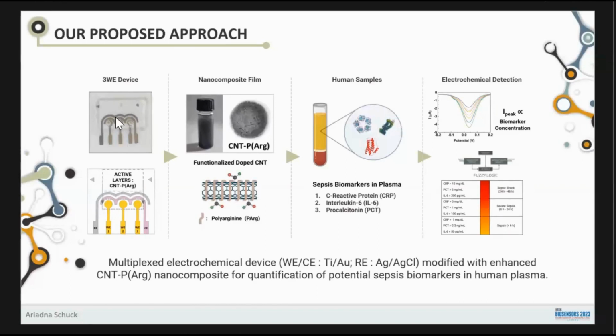But when I put the plasma sample, around 20 microliters, the sample flows through these microchannels and goes over the 3 active layers. So I have a multiplex measurement for the electrochemical. I decided to use differential pulse voltammetry for this. And then I get a response that is proportional to the concentration of each channel that I'm using here.